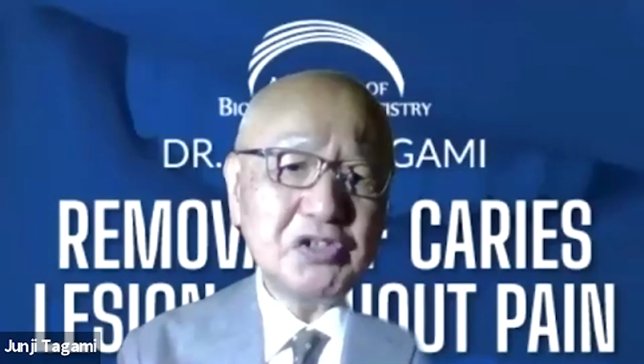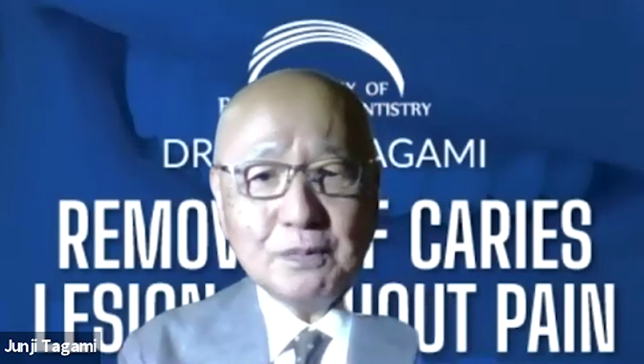Dr. Tagami, after you apply your thin layer of flowable resin on your hybrid layer, do you feel we have to wait, give it time? No, I cannot wait in the clinic. Okay, so we can go ahead and immediately start with the incremental technique. Yes, at first we apply light irradiation onto the bonding resin. And at that time, I try to apply two or three times of irradiation to make sure of the polymerization of the bonding. Then we apply the flowable composite and apply the light curing again.